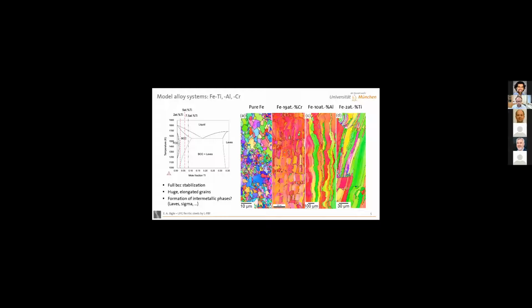So this is why we became interested in ferritic steels, because we said, well, this is as simple as it gets. You solidify fully as BCC, and above a certain concentration, for example, titanium here on the left, you constrict the austenite field enough that you stay completely ferritic as you cool down. Of course you can't overdo this. If you alloy too much, at some point you will get into intermetallic phases, for example, in this case, the Laves phase. With chromium, you could potentially get the sigma phase and so on and so forth. So that's just as a foreshadowing for later.